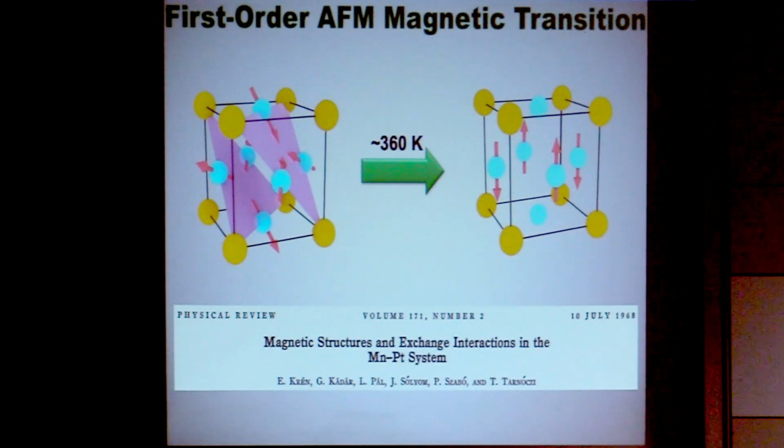We also worked on another antiferromagnet, Mn3Pt, because in single crystals it is very difficult to observe the anomalous Hall effect; it is difficult to realize strict cubic symmetry in thin films. So we started to grow these Mn3Pt thin films, because this material is quite similar to iron rhodium. It has a first-order magnetic phase transition, but this is an antiferromagnetic to antiferromagnetic phase transition.